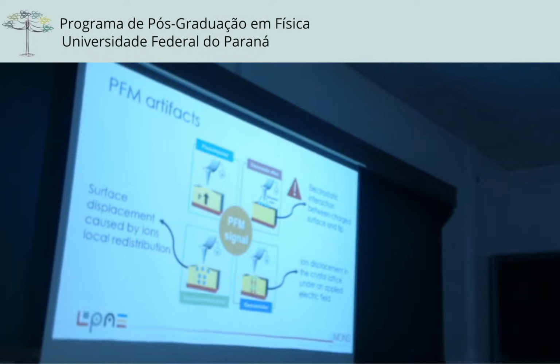This is the worst measurement you may do with scanning probe microscopy, the piezo. It's extremely complex, because there are plenty of artifacts. You have electrostatic effect, because the cantilever is collecting, and you are measuring at the apex. If you are not shielding the tip, you are also measuring the contribution of that, and the tip doesn't care. There is an electrostatic force, I'm going down, up, or down, and this is what you are measuring. So extracting the D33, the piezoelectric coefficient, is extremely complicated. There are also plenty of electrochemical strain, electrostriction, and so on.